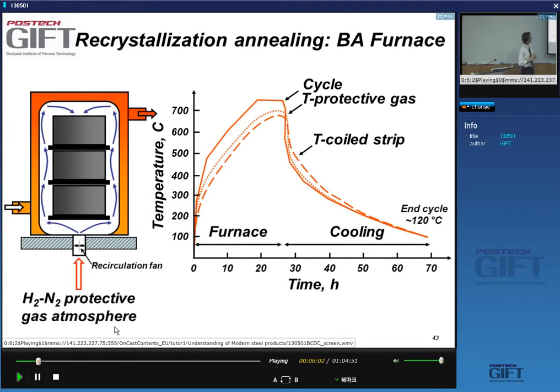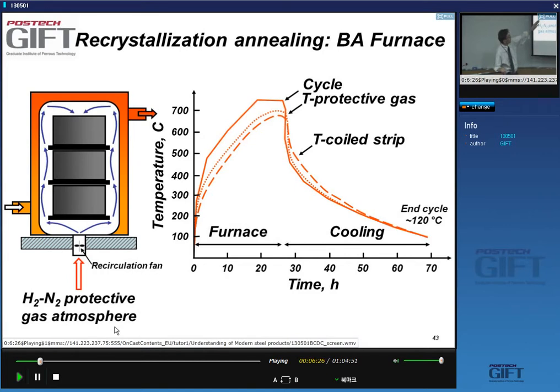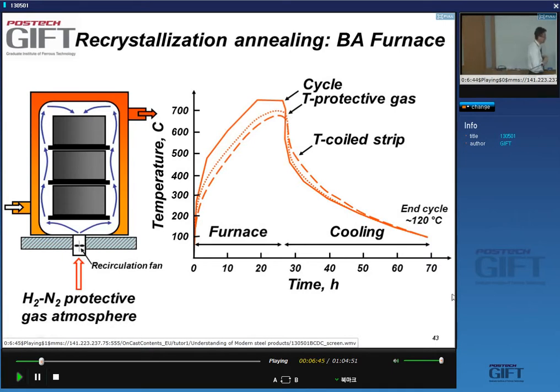Your stacked coils are in a protective atmosphere of hydrogen and nitrogen, and this enclosure is itself enclosed into a furnace where you heat the material with gas burners. Because you have such a high mass of coiled materials, it takes time to accomplish the process — easily a whole day to reach the maximum temperature inside the coil, and then even more time to cool it.